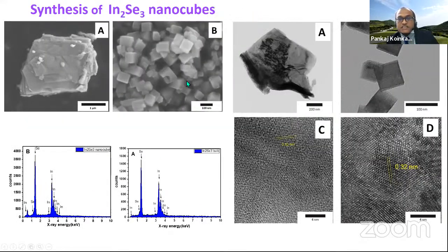This sheet material is totally transformed into the cube. So this is an SEM image, you can see some cubes, and this is a TEM image. So the bulk material, and this is the cube. So you can see these are the cubes. And we have confirmed through EDAX whether indium and selenide are still present.